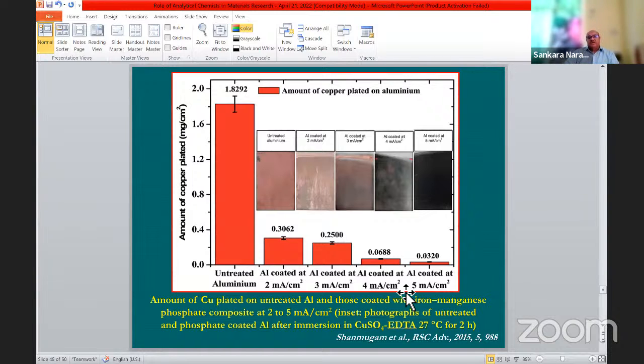We prepared the coating by an electrochemical method. We applied different current densities and coated the sample. And this is the uncoated aluminium sample. If we immerse it in a copper sulfate EDTA solution for 2 hours, the amount of copper that is plated, you can determine by weight gain, or you can strip it and analyze by AAS also. The amount of copper deposited on untreated aluminium is very high, about 1.82. But if you coat the aluminium with a phosphate coating, you can see a considerable reduction in the copper deposit, because most of the areas are covered by the phosphate coating. Only a few spots are left, and only those areas are copper plated.